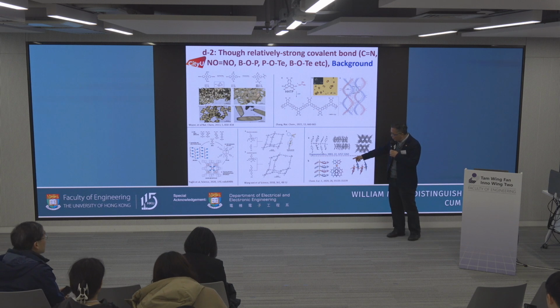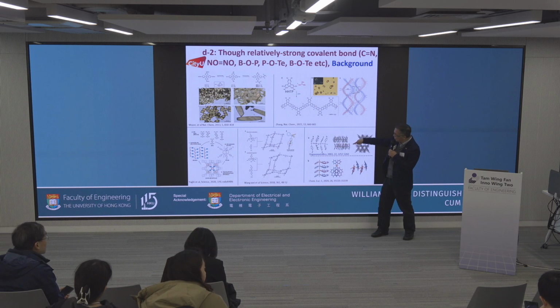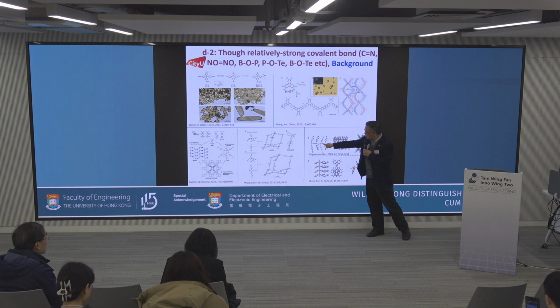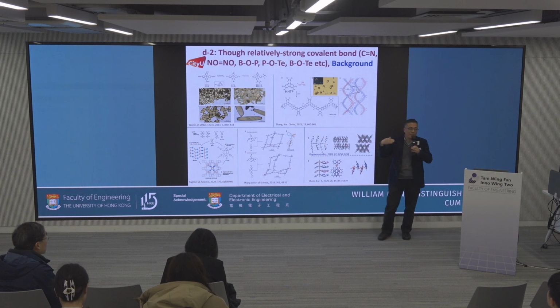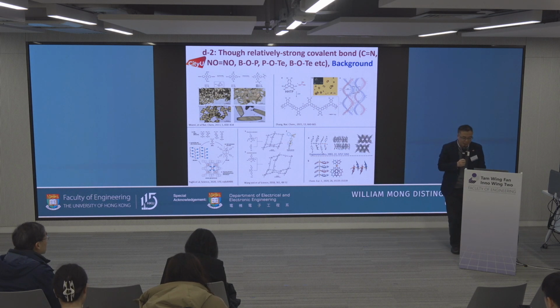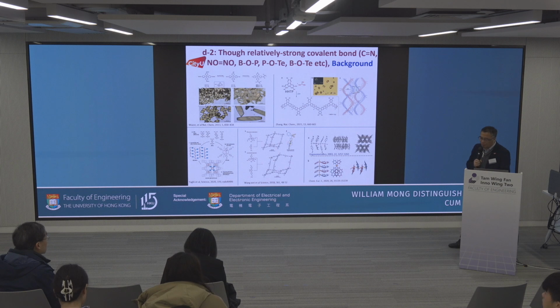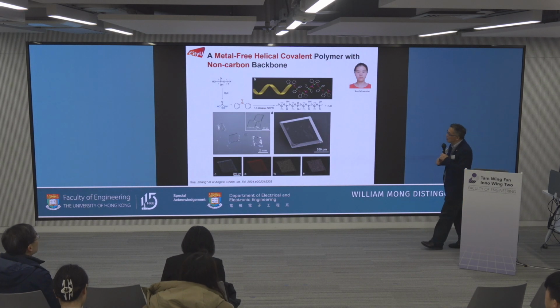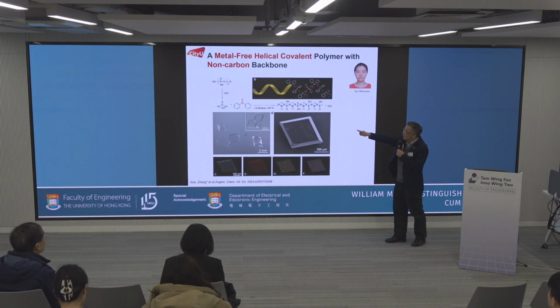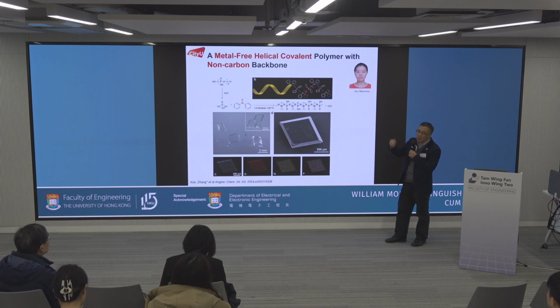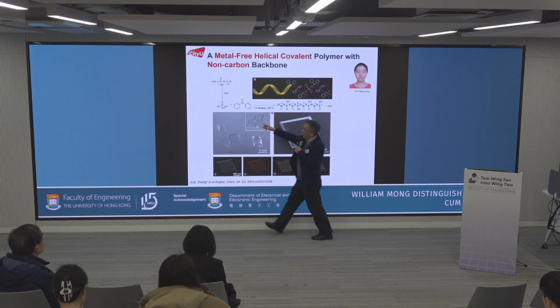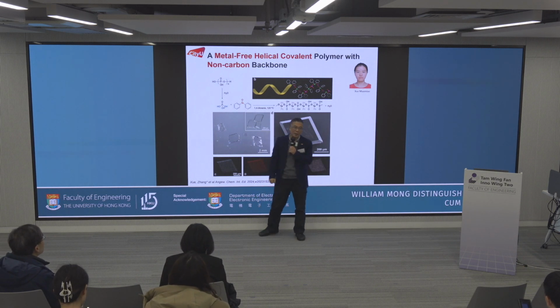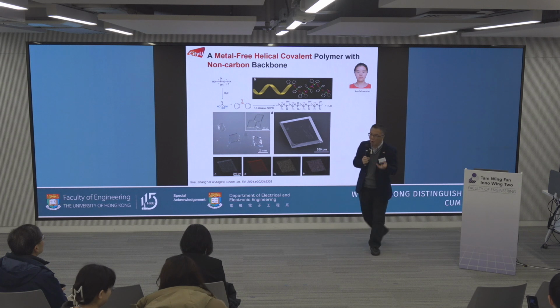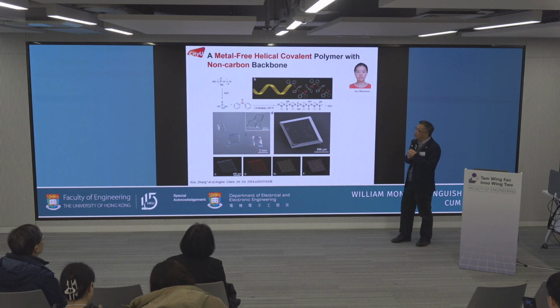So what is shown here, actually, these people reported that they use a tellurium oxide, which can self-assemble, they form the tellurium oxide chain. So from this idea, what I'm thinking is, is it possible for us to use diphenyl tellurium oxide and then react with inorganic phosphoric acid? Is it possible that works or not? If it works, then we can change the inorganic phosphate to organic phosphate, and we can make a lot of polymer or organic polymer structures.